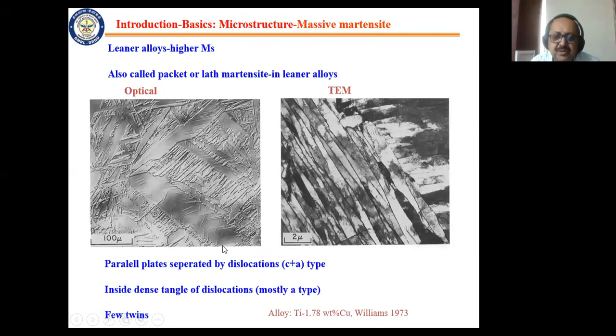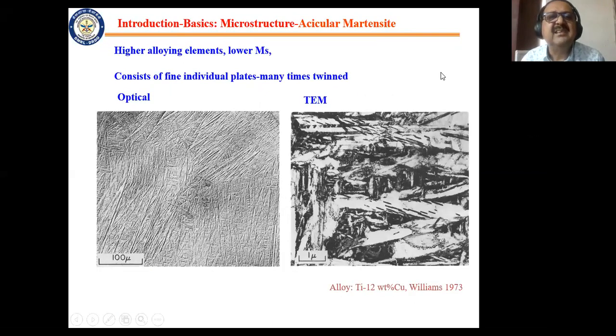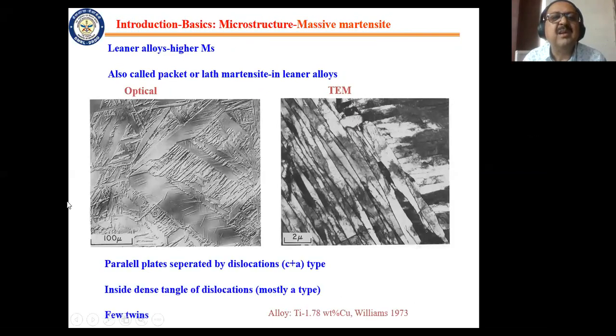Now I will just introduce you to titanium martensite, because everybody knows steel martensite. First is what is known as lath or packet martensite, and this happens in leaner alloys that have a lower amount of alloying elements. Like this is an example of titanium with 1.78 weight% copper, and when you quench it after beta treatment, you get this kind of microstructure. This is known as lath martensite and occurs in leaner alloys.